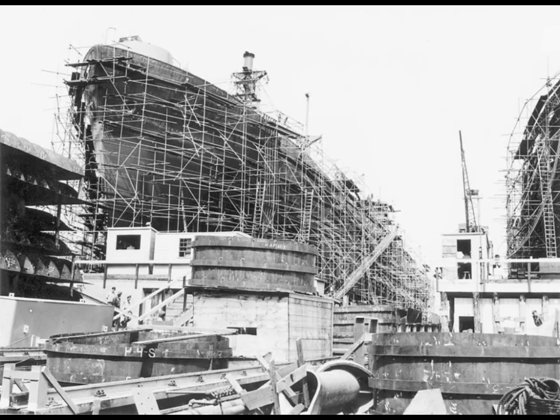Investigation revealed the steel had a ductile to brittle transition temperature that was too high. In cold water, the steel became brittle. Stress concentration at welded corners propagated cracks. The crack would race across a welded plate faster than it would in riveted construction because welded plates were continuous rather than interrupted by rivet holes.